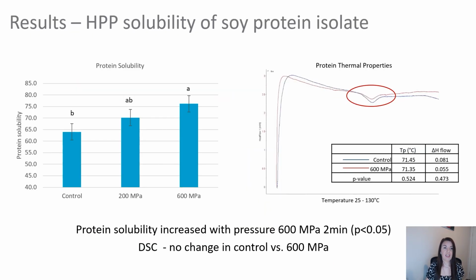So here you can see the results of HPP on protein solubility. When we applied high pressure processing at 200 or 600 megapascals, ambient temperature, for 2 minutes to soy protein isolate, we did have a significant effect on the solubility, especially at 600 megapascals. And when we used differential scanning calorimetry to see if this affected the denaturation, you can see here that the red and the blue line with the circle are similar, they're having similar enthalpy. So therefore, we couldn't really pinpoint what was the reason for this change in solubility.